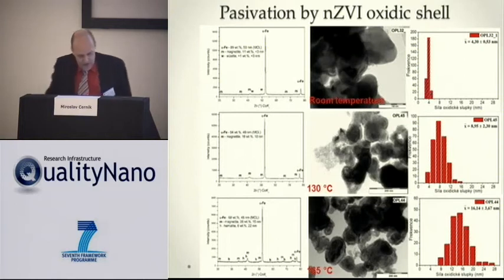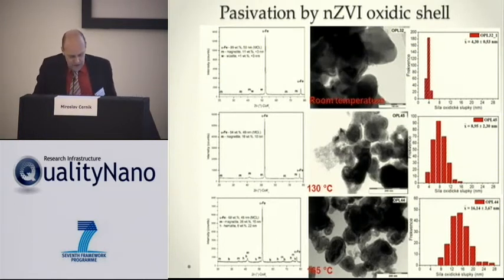And on the picture on the right you have the thickness of the shell, so that if we increase the temperature, the thickness of the shell increases, so the protection of the particles is higher, and we need to find the condition where the thickness of the shell is sufficient to protect the particles, but on the other hand does not decrease their reactivity.